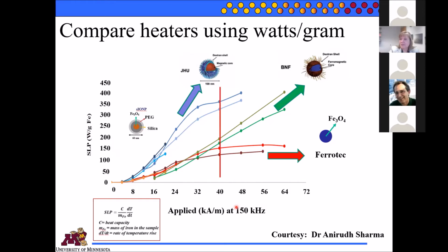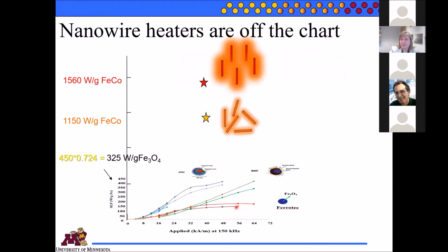So if we want to take a look now at 40 kiloamp per meter, that's really the maximum that we'd like to use, because we can design a coercivity less than that. Now, it's nice to see that nanowires, as far as heating goes on this measure when we're comparing particles, are really off the scale, which again you'd probably expect if you go with a very high moment magnetic material.